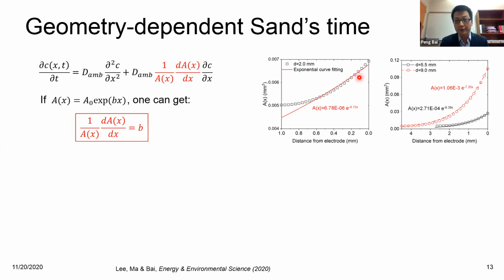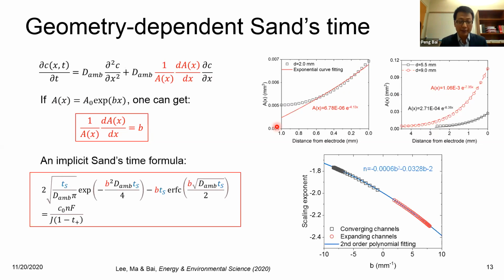So we did this. For different types of capillaries, we can use this exponential equation to approximate the area change pretty closely. And you can see that we were able to find an implicit but analytical Sand's time formula. And on this chart, you can see that it indeed depends on the convergence rate of your channel. You will get a positively deviated exponent or a negatively deviated exponent. So that gives us the confidence that you really can rely on the structure, just a static structure. If it can promote some beneficial transfer process, it can change the dynamic metal penetration process.